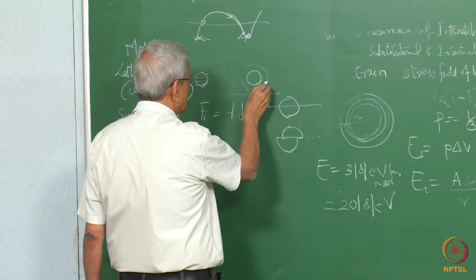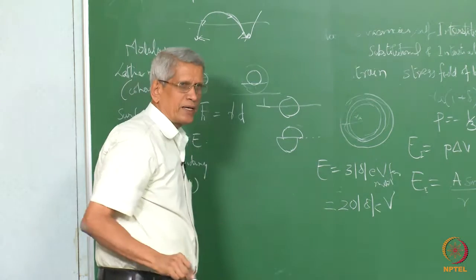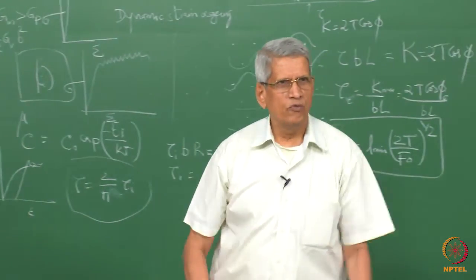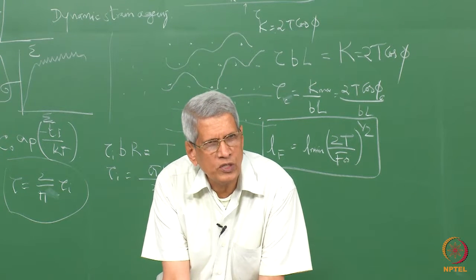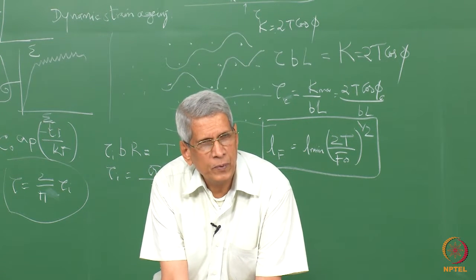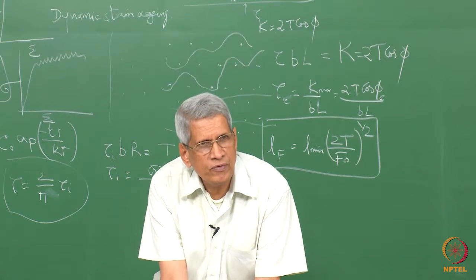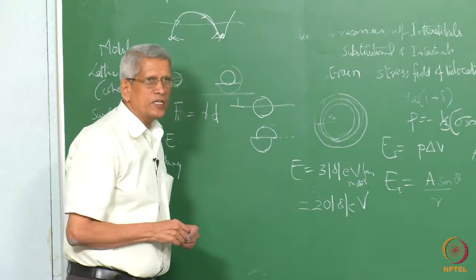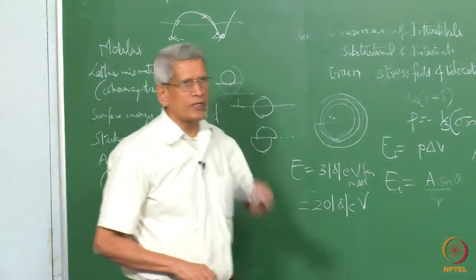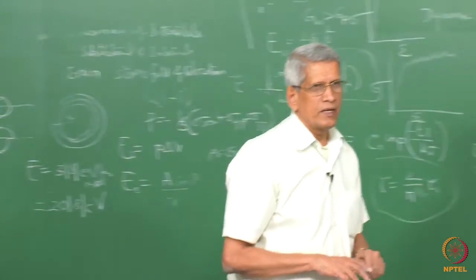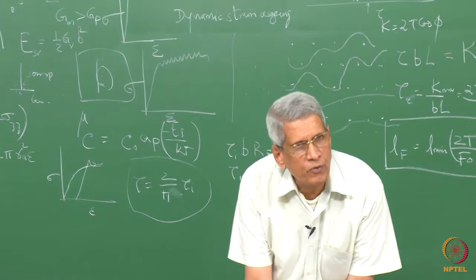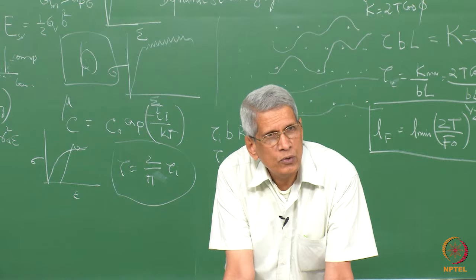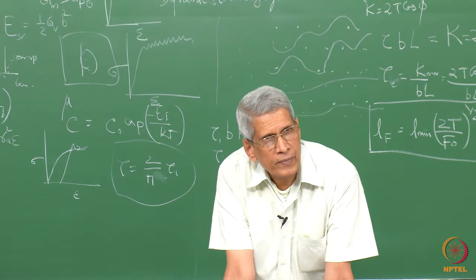Order hardening will act only when the dislocation tries to enter the particle. So all these effects act at different instants and at different positions with respect to the particle. The sum of the effects at each point keeps changing and reaches a maximum value at some particular point. That maximum value is the stress required for the dislocation to overcome the particle.